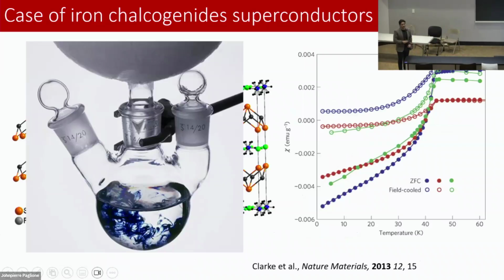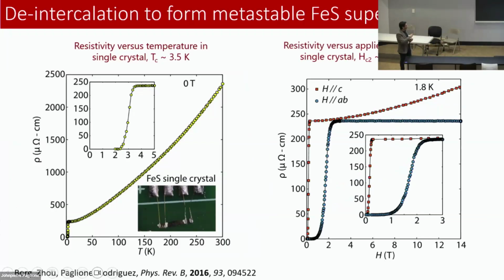You take ammonia and you liquefy it, and the blue color is actually from a solvated electron. As you put lithium or sodium or any alkali metal, you solvate the electron, which immediately reduces the iron selenide, turns it anionic, and then it intercalates a cation inside. So it's actually pretty interesting chemistry in itself.